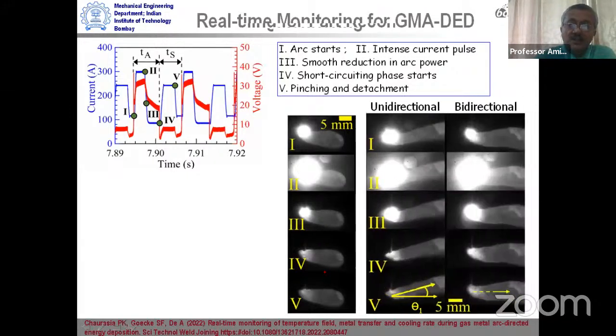Typically, in a unidirectional scanning, it's going on in this manner. In a bidirectional scanning, we see the pool as it is depositing from right to left, it's having a much more uniform build pool. It's obvious because in a unidirectional scanning strategy, it is already realized that there will be a huge amount of build asymmetry because of asymmetric distribution of heat. In contrast, if we do a bidirectional scanning, there is an even distribution of heat through the length of the tracks, so it automatically becomes a much easier, much more uniform deposition.